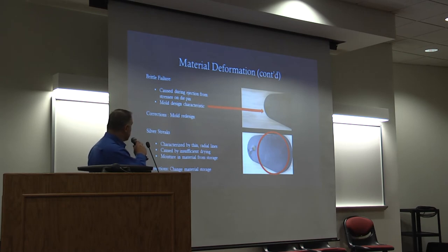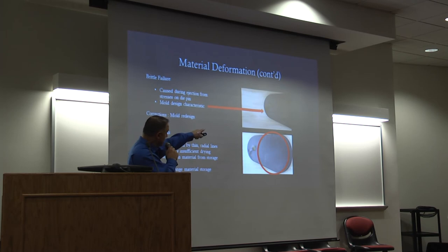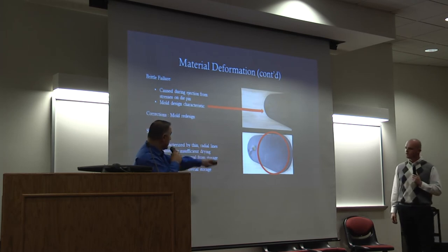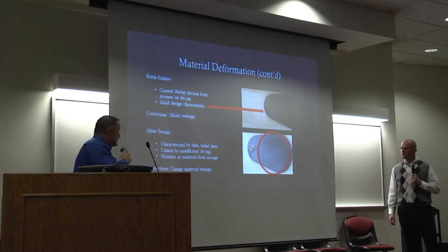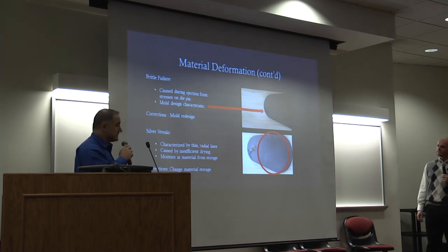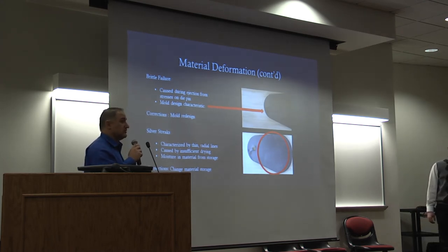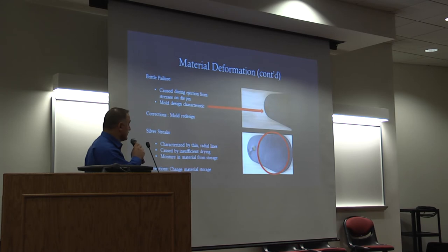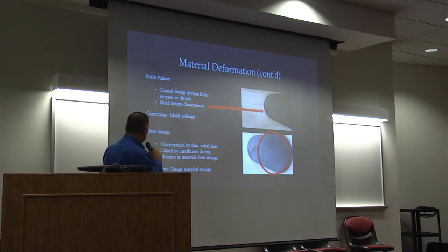Another failure that we noticed was a brittle failure, which you can see by the arrow up top and also by the bottom. This is caused by the stresses being placed on the pin within the mold, which makes that circle. As it's being injected, the material is not completely fully formed and set up, and it's causing stresses on that point.